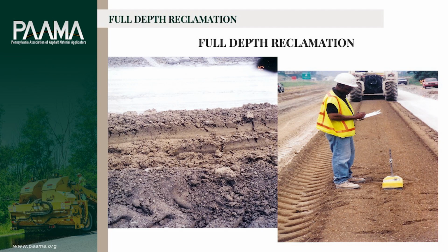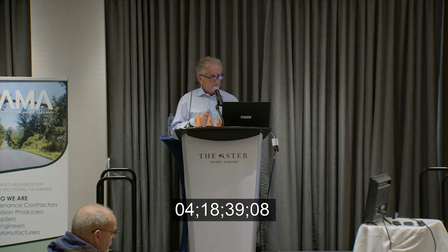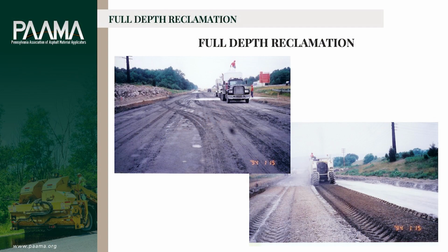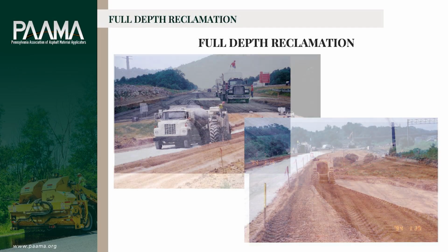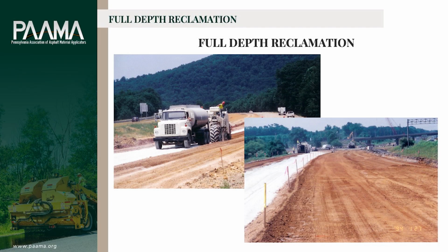That gentleman there is just doing a backscatter with his nuclear gauge, finding out the moisture content. He had to control the moisture on the project. Here, that top left-hand photo is the fly ash. It's black, you know, it's out of a power plant. So that's the color, and then the lime was placed directly on top of the fly ash, and then the combination, they were both mixed in together, and they were mixed with the reclaimer. Water was added. We had to keep a certain moisture content, and Alan Myers did the grading behind and the compaction.